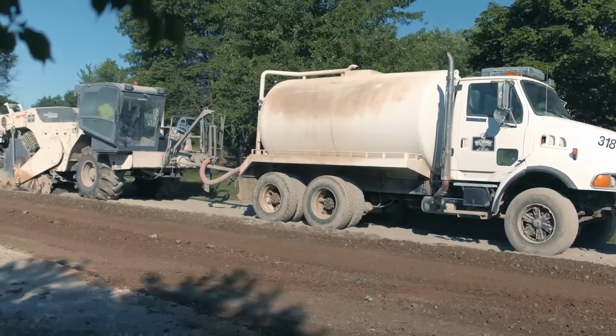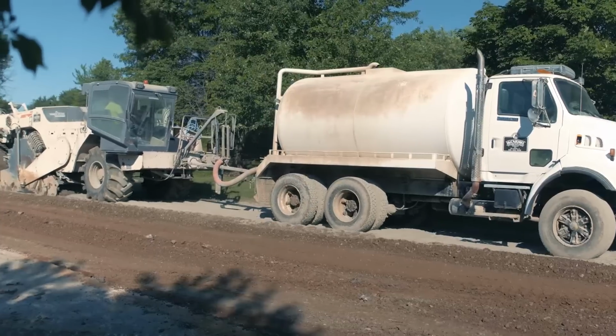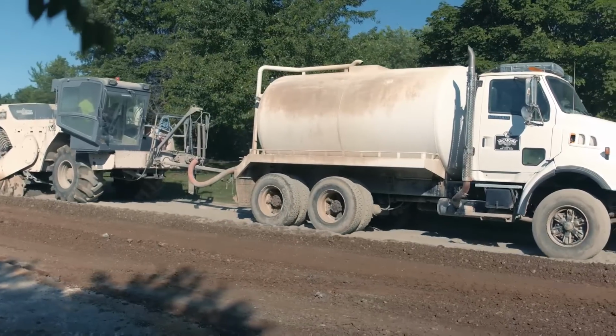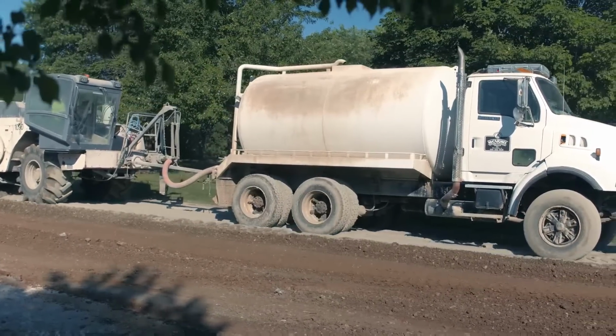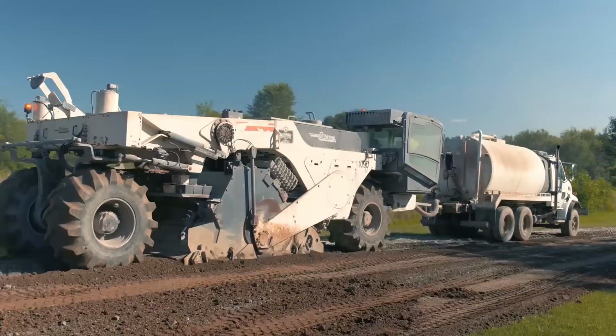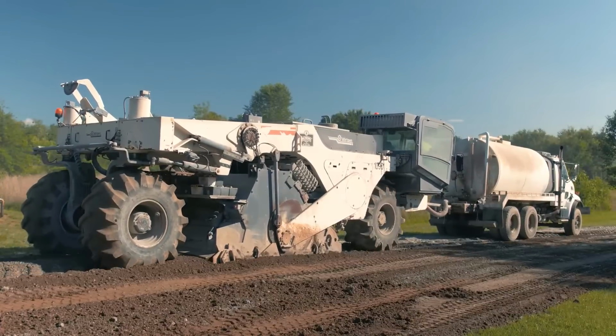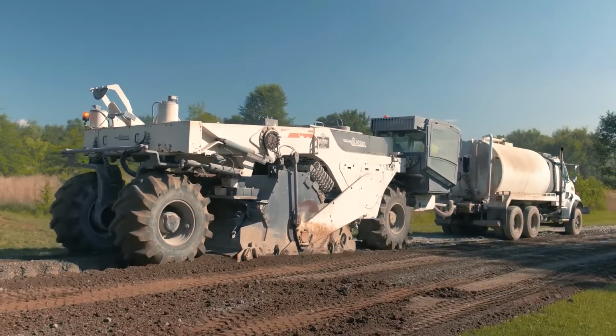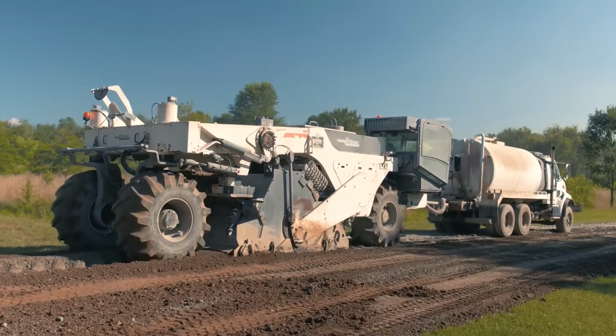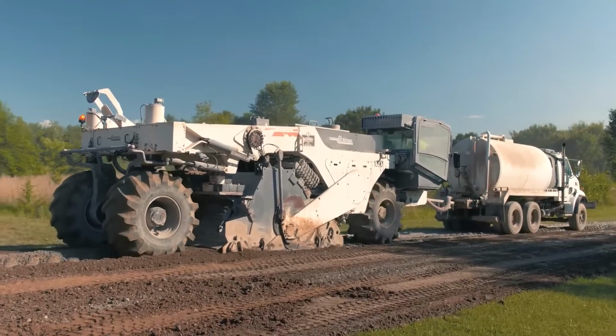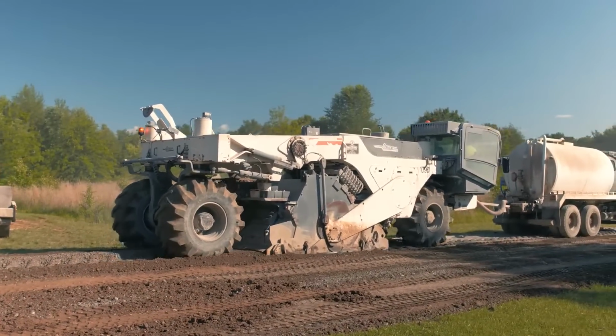On this project, the cement application rate was 6%, which is a common and effective application rate for FDR with cement. The cement is mixed with the existing base to the full depth of treatment, with water being added through the mixing drum to hydrate the cement and bring the mixture to optimum moisture content.